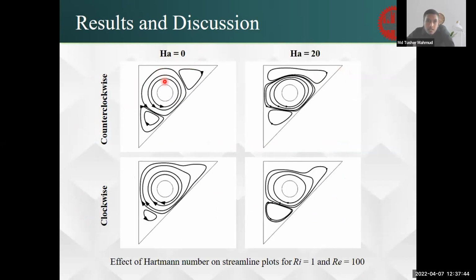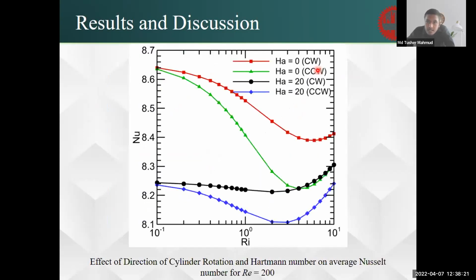Now if we use the Hartmann number, which is the magnetic effect, we have used a magnetic field from left to right. Under the magnetic field, the streamlines get distorted, and the magnetic field actually prevents the flow from being random and tries to stabilize it. So if we use a magnetic field, then the heat transfer is affected. Here are the isotherm plots, with and without Hartmann number, which means with and without a magnetic field from left to right. The Nusselt number is decreased as the flow is stabilized by the magnetic field. So the heat transfer rate is higher in a system without MHD effect.